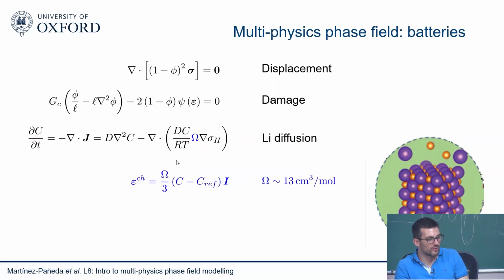In our case, for the fatigue problem, we solve either fully coupled, so everything monolithically, but we have also solved problems staggered depending on what. I think for the full electro calculations, it was a bit faster to solve the problem staggered. But the stiffness itself is still a constant. It's not going to change as a function of the lithium. No. So the only thing that would change the stiffness will be the phase field. Yeah. So that's the degradation of the stiffness. But yeah, they will not be changed.